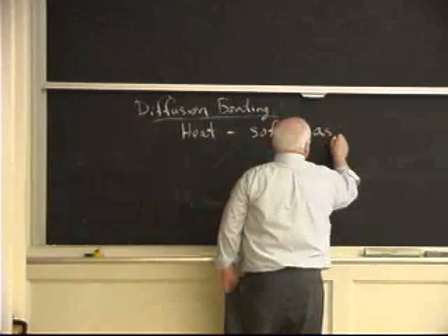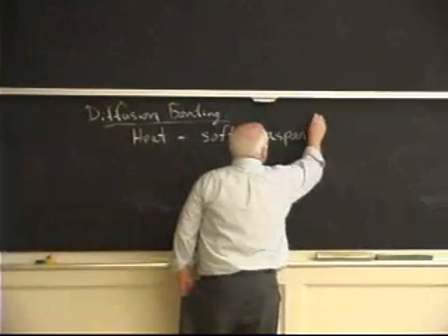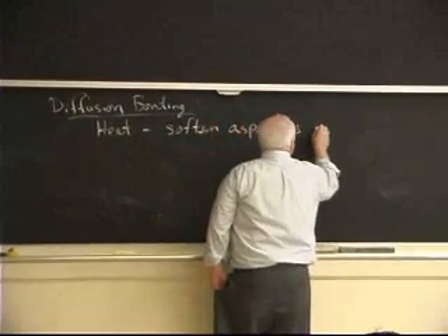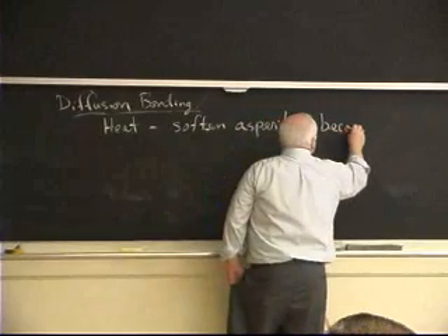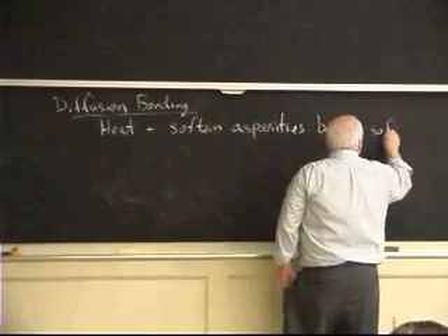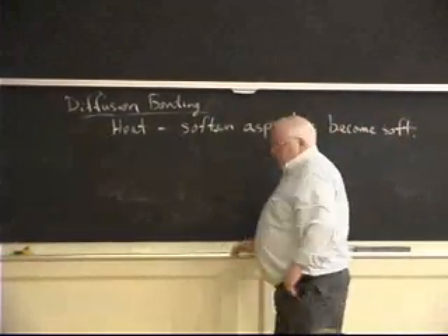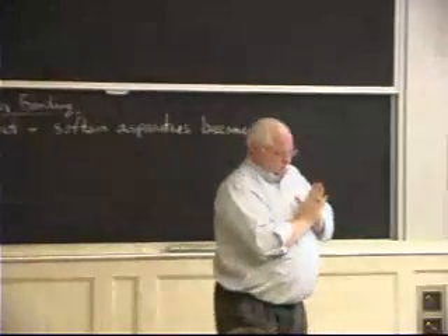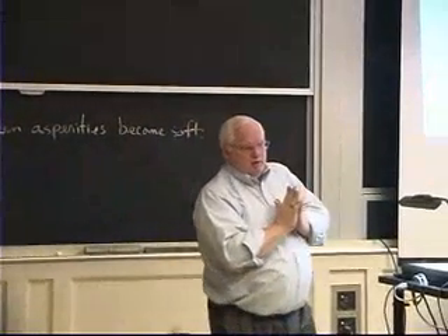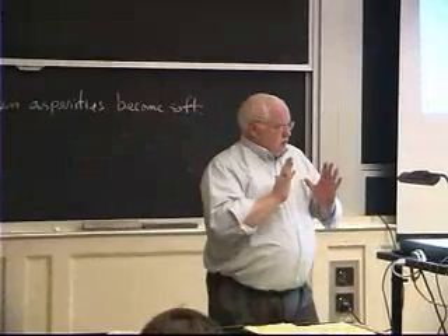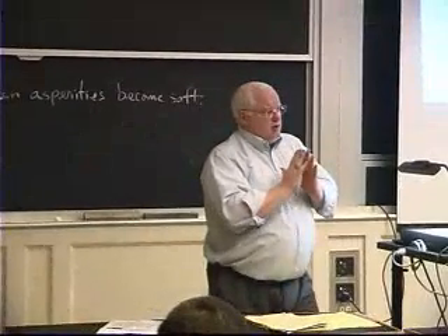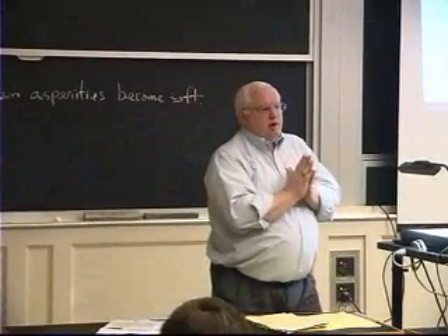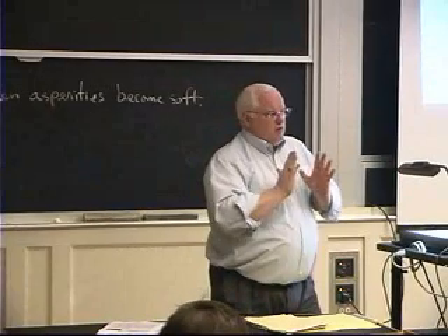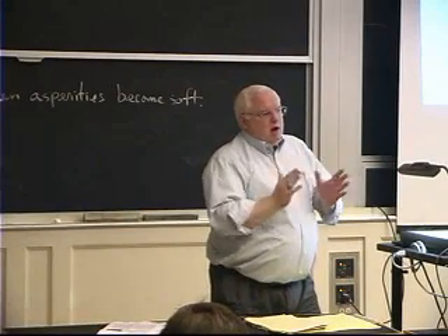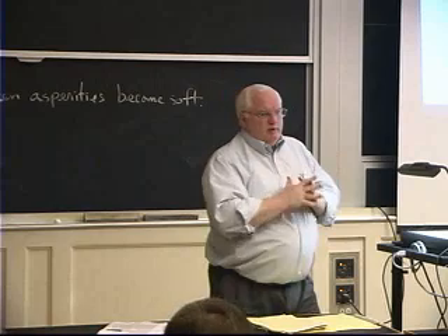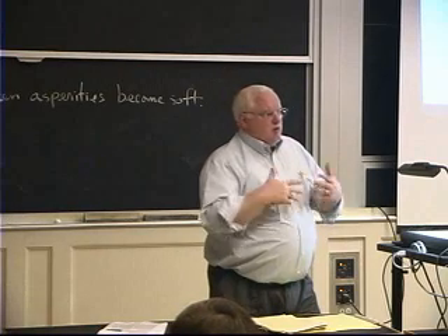So these asperities or mountain peaks become soft. And we're going to basically push it over time. I'm going to hold the pressure on there for a fair amount of time, and that's going to allow us to essentially slowly get rid of those mountain peaks and get a larger than 30% contact area because the stuff is slowly deforming. So you get higher contact area because the heat allows things to soften and start to flow over time. You get what's called creep.